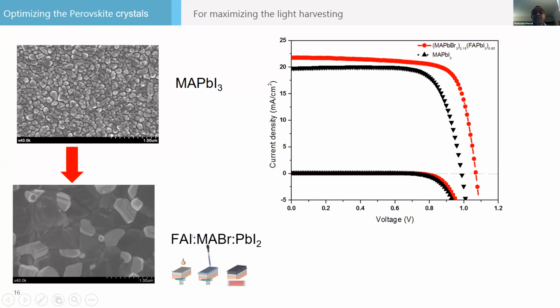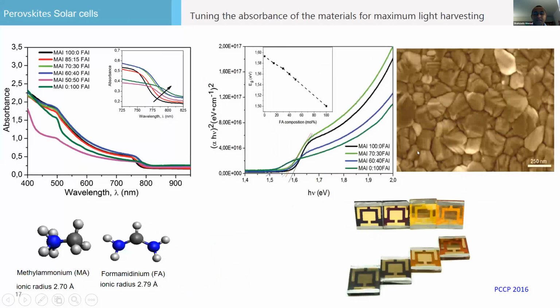So now we take a composition of a cocktail. So this is formamidinium iodide. Then we have methyl ammonium bromide for higher voltage, and lead iodide. So when we took a cocktail, we can see the crystals are larger. Now we are even getting much larger crystals, just for a representation, and the grain boundaries are less. And you can see we have a jump in both current as well as the voltage.